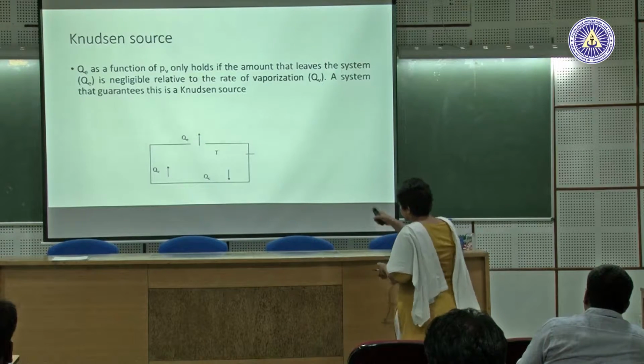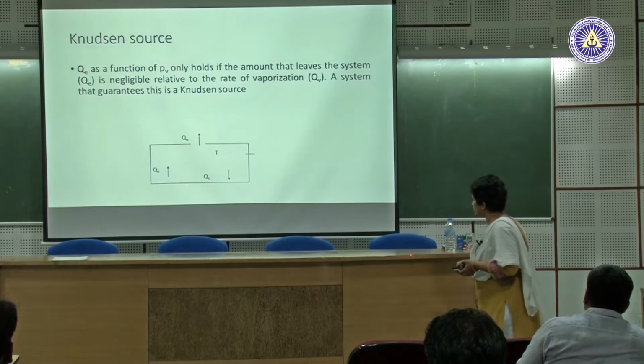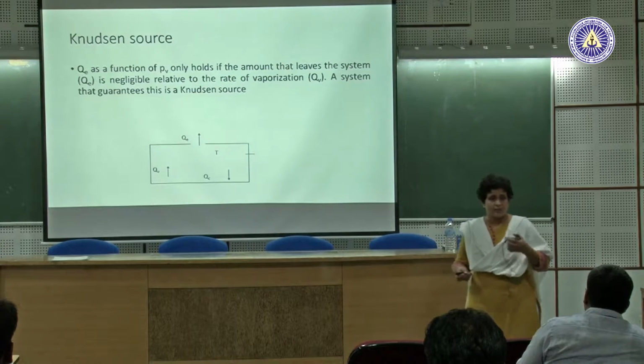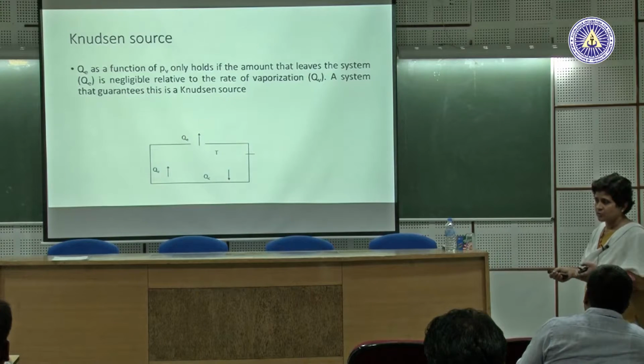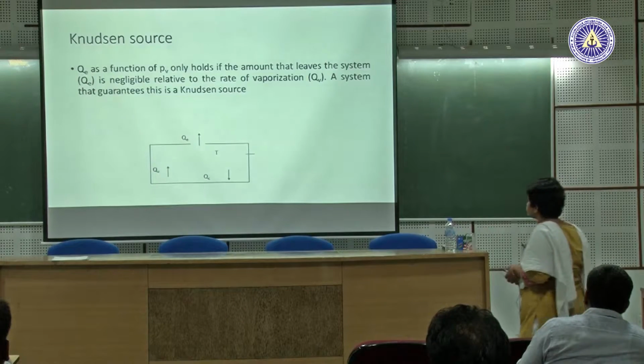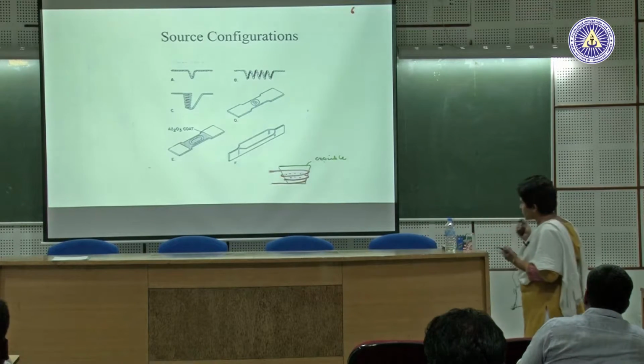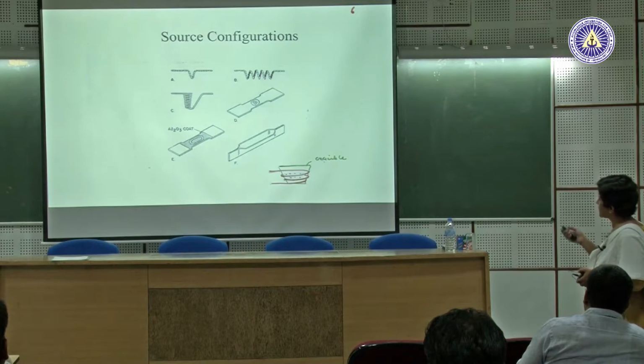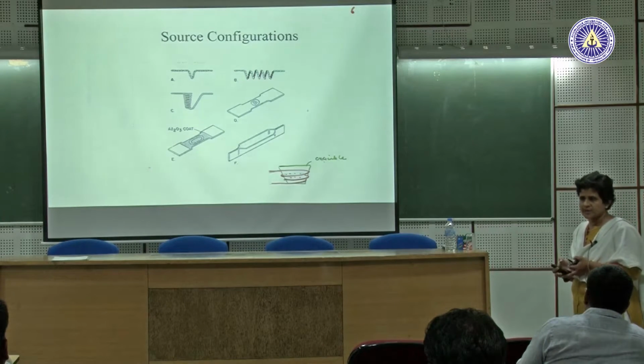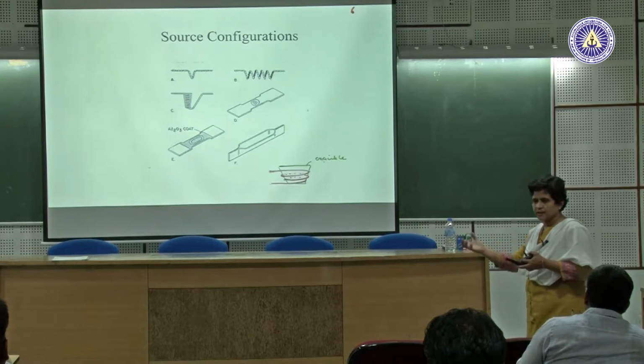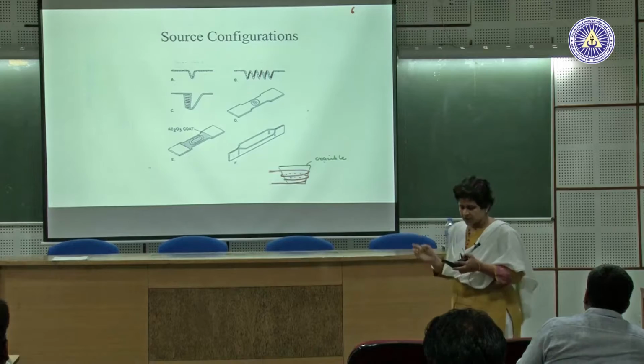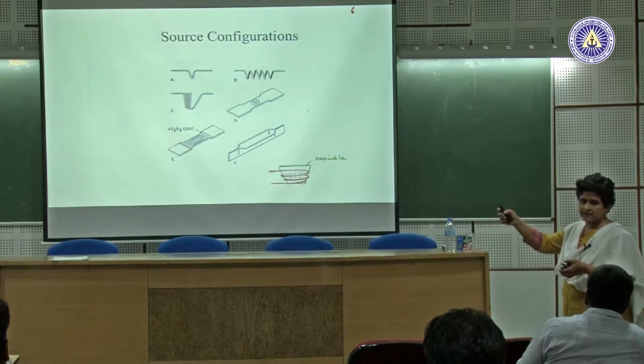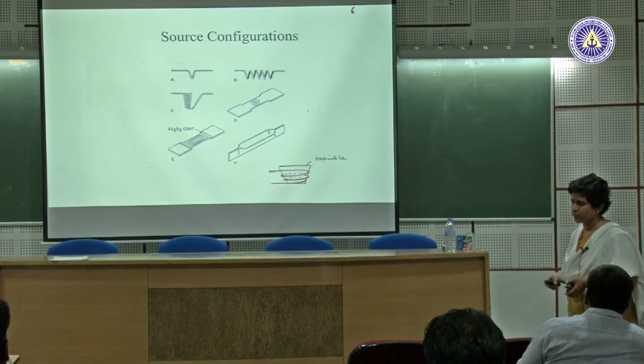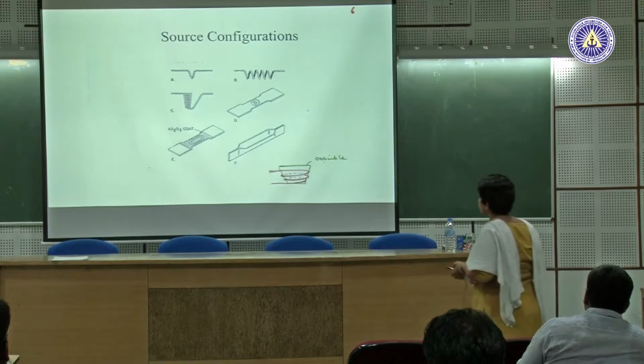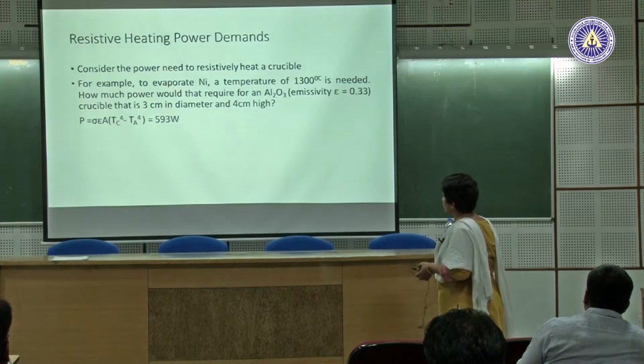So, that kind of sources are there which are closed, and the temperature is monitored within a fraction of a degree centigrade, so that your source always gives you a controlled amount of deposition rate. If you just want some sort of evaporation, you can use even some tungsten coils. You can just hang some aluminum wires on it, heat it up, it would just evaporate and give you a nice film. So these are simple examples. On the other end is the very controlled one, which runs into crores to buy an equipment which has a very controlled evaporation rate. So you have the whole range of equipment depending on the control that you want.